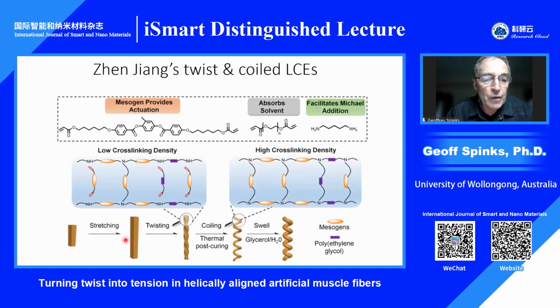material first to be stretched to align the mesogens, then twisted and coiled. Before, at this point, the cross-linking is allowed to be completed to lock in the alignment, the twist, and the coiling into a stable structure. We then swelled these samples in water or glycerol for stability, to reduce their modulus.